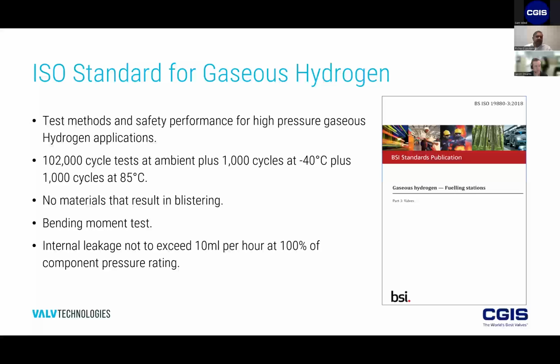We tend to see a lot of tubing being used instead of piping. So from what we've seen, it tends to be the tubing that's more the limiting factor than the valve itself. But overall, the standard still has what it defines as an acceptable rate of leakage, and it's about 10 milliliters per hour at 100% of the cold working pressure.